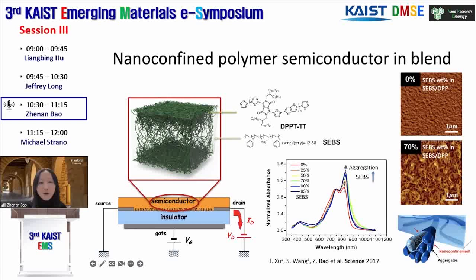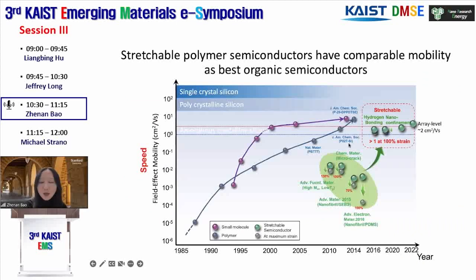And of course, the details of film formation are also important because these nano-confined structures need to be interconnected and in good contact with each other when the film is being formed. But with proper tuning, we are able to obtain such structures, with a boost in the charge transport instead of a decrease in the charge transport. And at the same time, we obtain the stretchability.